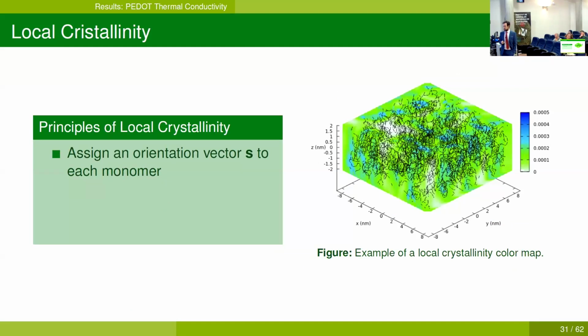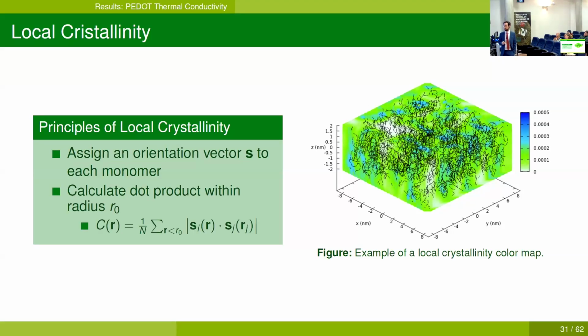We have also defined a custom measure that we called local crystallinity measurement, where basically we assign a vector S to each monomer along the backbone direction, and they are depicted here. So the black dotted lines are PEDOT chains, and each dot represents a monomer, and if you follow the dots, you see how the PEDOT chains are conformed here in the sample. And what we do is we calculate the dot product within a certain radius with the following formula.